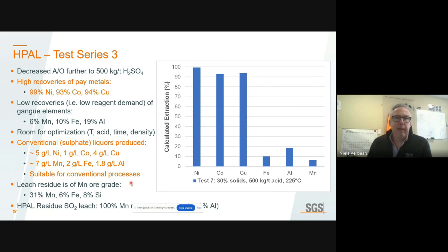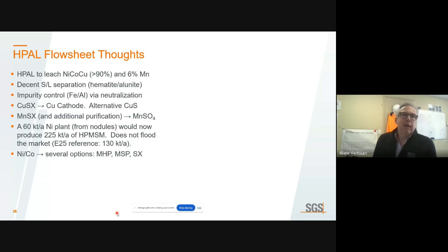And we did do some leach work on that residue. In a single test, we were able to show that we can recover 100% of the manganese using a mild reductive leach test. So some thoughts here on what this flow sheet might look like.